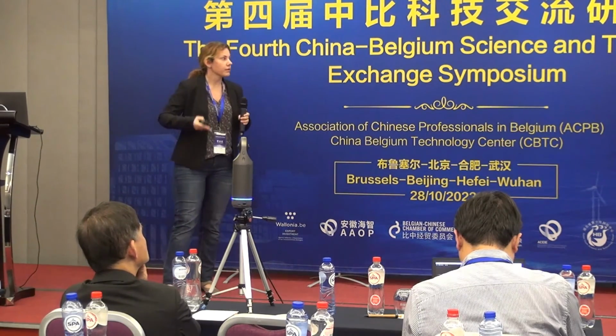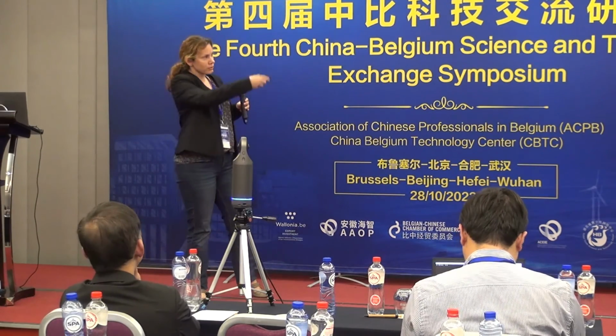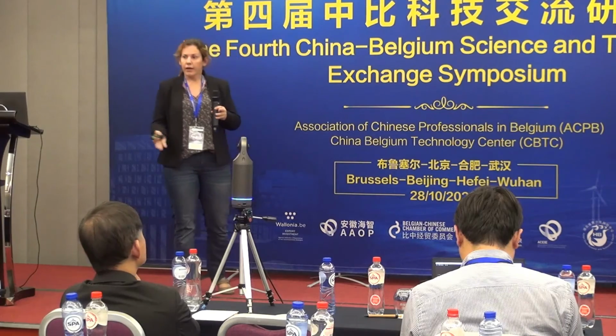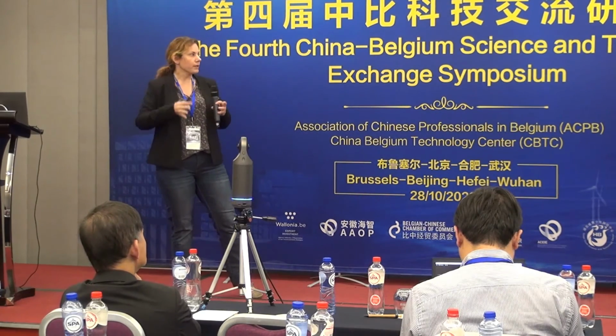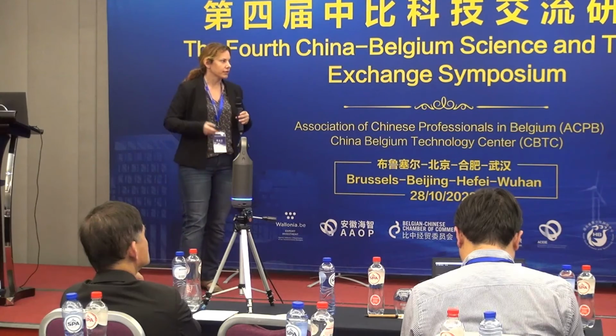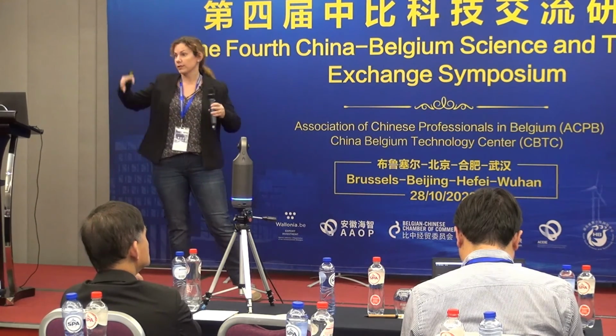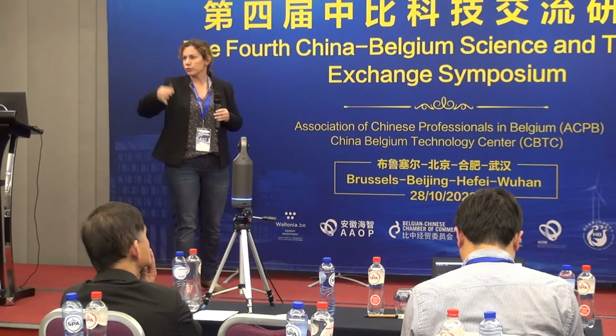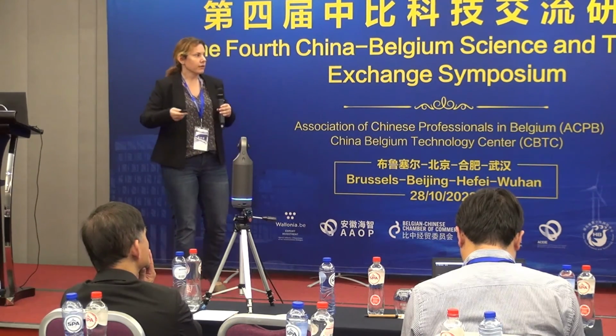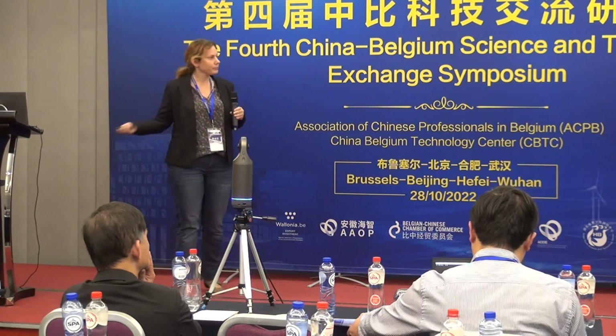So you take your slag chemistry, additives, alkali activation, and you look at some ratios. There are silica to potassium, alumina to potassium, etc. And you basically make different mix designs, and you look at the crystallization behavior and at the phase assemblages at high temperature. You want to know what the melting temperatures of these phases are, and then basically you pick the right mix design for your application.